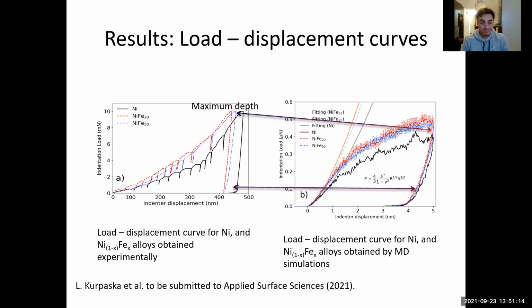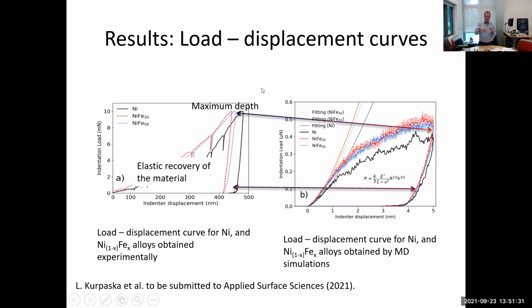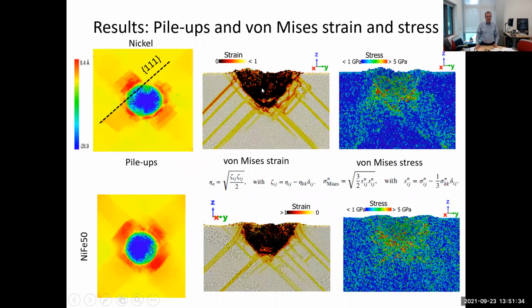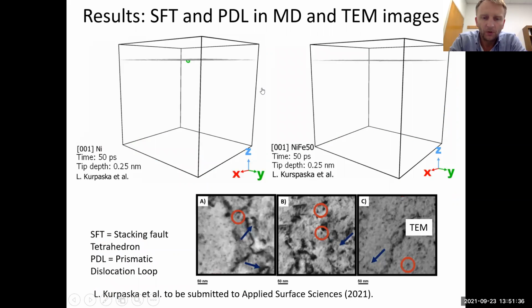Then also, not being a material scientist, the TEM images were really interesting. They showed almost a pyramidal shape. And I initially had the impression that the indenter experimentally was like a sharp tip. But is that just because of the cubic structure of the material? This is not in situ TEM. This is TEM recorded after the experiment, so the structure is already plastically deformed.